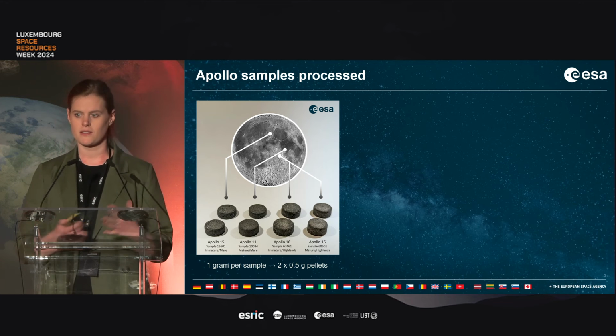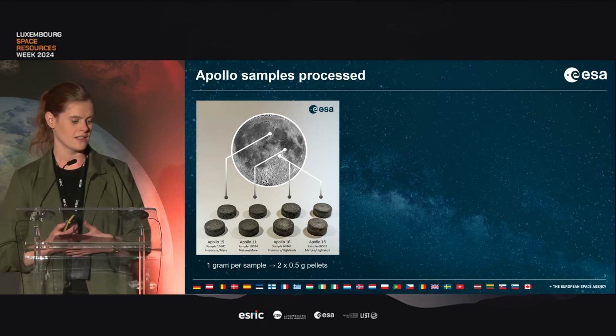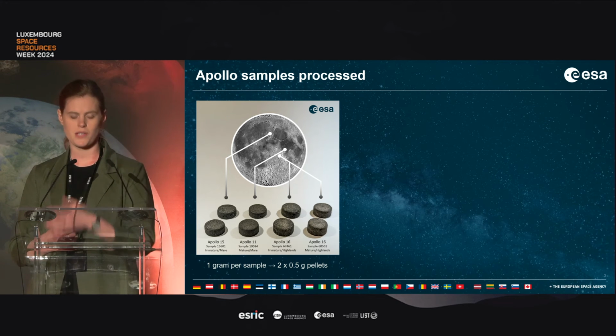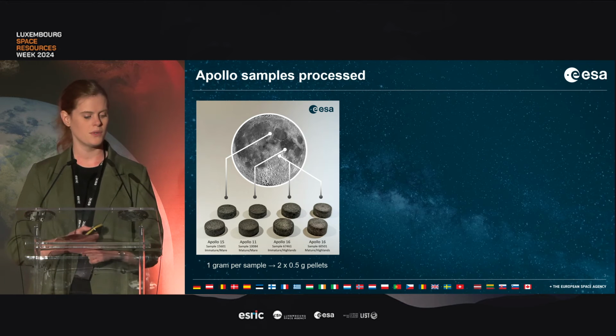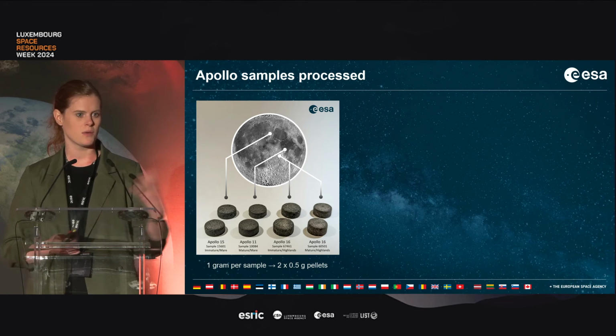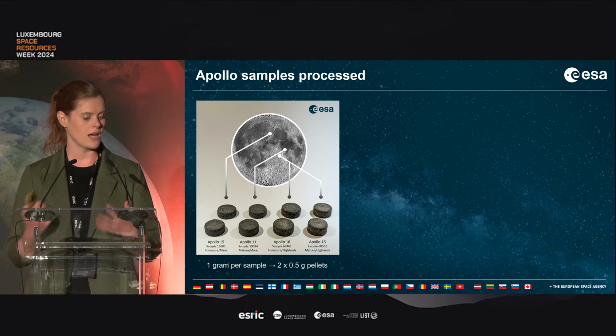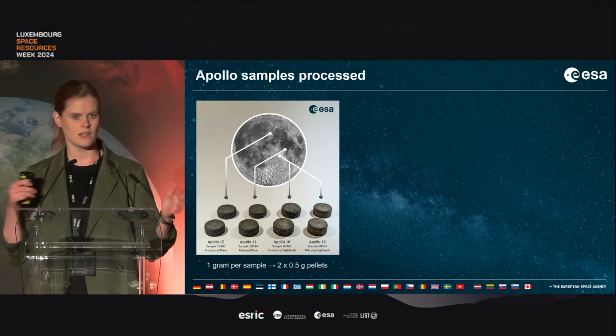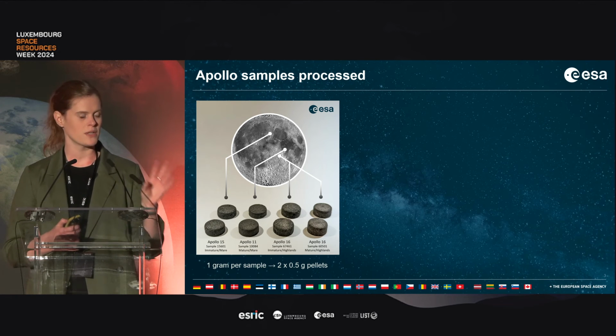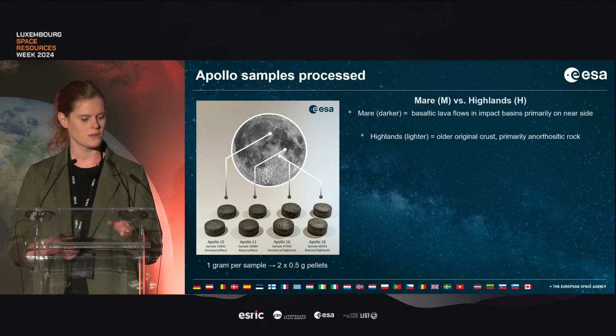So onto the samples that we used as a feedstock. We were lucky enough to be allocated 4 Apollo samples, 1 gram per sample. And so we got 2 Mare materials, Apollo 15 and Apollo 11, and 2 Highland materials. So for each category, we requested an immature and a mature sample.